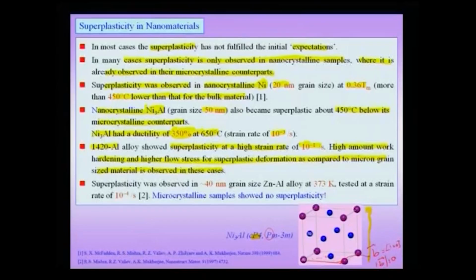The high amount of work hardening also implies that there is an accumulation of what you may call dislocation density, which is actually hardening the material. And here also you observe that the stress for superplastic forming is higher than its micron sized counterparts.